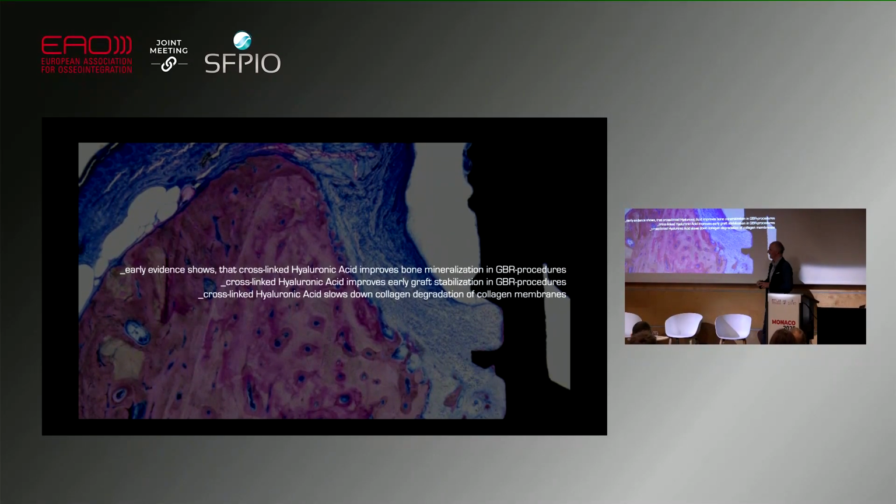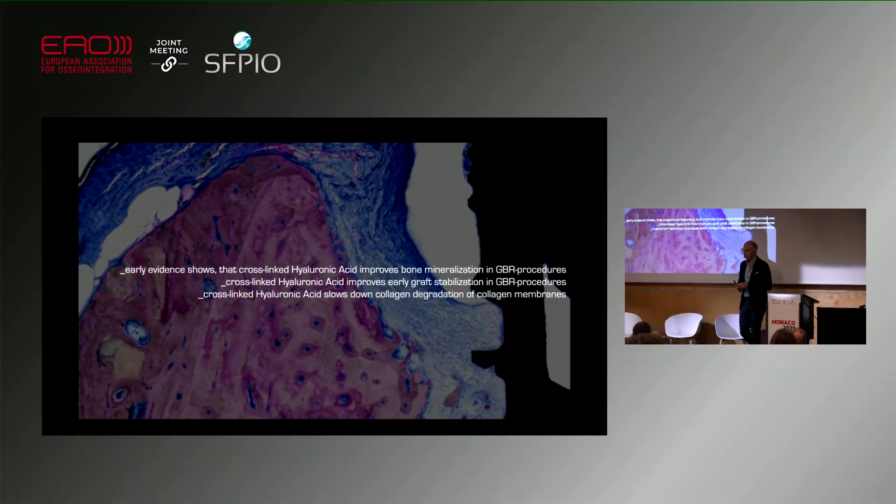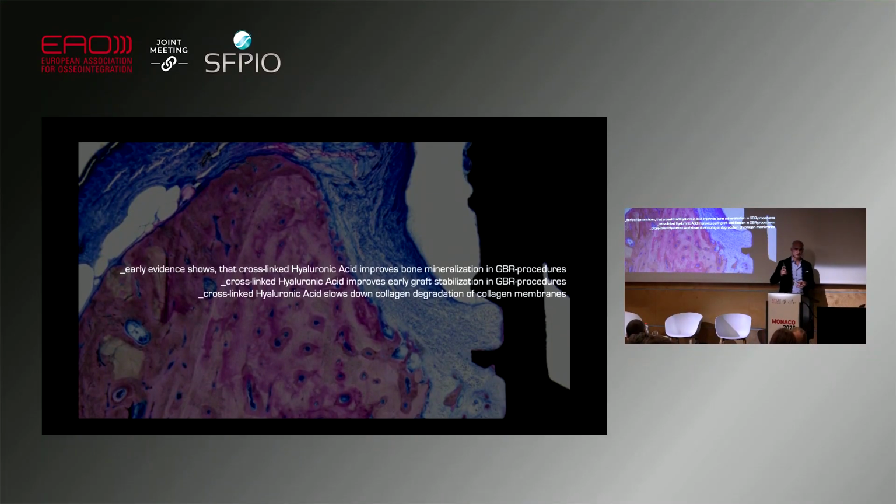We have to work on that, but we definitely see that cross-linked hyaluronic acid improves bone mineralization. We definitely see that we have more vital bone and less remnant particles. We also see that graft stabilization helps us, and mechanical clotting definitely helps us. And we also see that hyaluronic acid slows down collagen degradation of membranes, and by this gives you a longer standing time of membranes. Thank you very much for your attention.